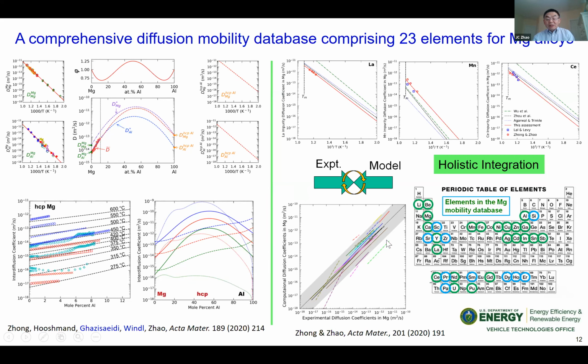So when the lines are parallel, that means the activation energy is exactly the same. When they are further away, the D0 is further away. So you can see that the D sub 0 has some variation, but the activation energy is quite accurate. So what we have done in that case is what I call holistic integration. Experimentally, using the liquid-solid diffusion couple, we can get high temperature data very fast. The diffusion takes only a few hours, and then we can get reliable data.